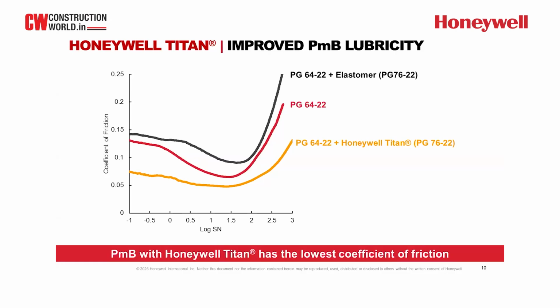They're both PG76-22. The top one is PG76-22 modified with an elastomer, SBS here. And the bottom one, the orange colored curve, is also a PG76-22, but modified with Honeywell Titan 7686. So it's a low molecular weight functionalized polyethylene. So that's the chemistry of Honeywell Titan 7686.